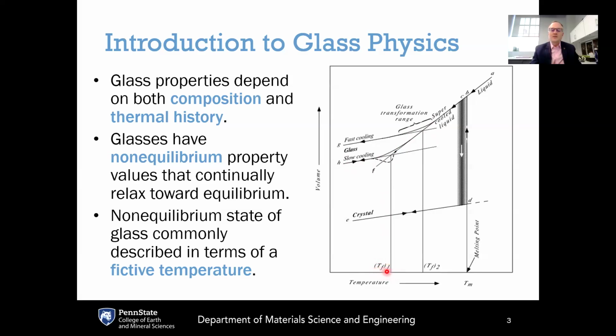So you can see that the fictive temperature of the slowly cooled glass is lower than the fictive temperature of the fast-cooled glass. And that's because the slower cooling rate gives the system more time to stay in its metastable supercooled liquid state and then only fall out of equilibrium at a lower fictive temperature. Fictive temperature is not a perfect means of describing the non-equilibrium state of the glass. It is merely a simple way to take one additional parameter and give some indication about where it's fallen out of equilibrium.